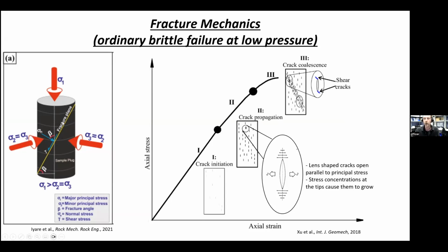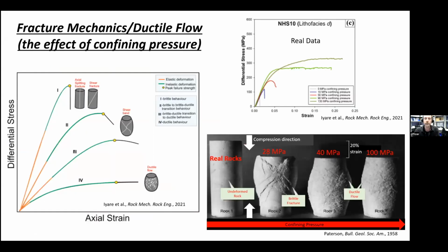So imagine you take this rock and you start to stress it in the sigma 1 direction. Well, what's going to happen is it's going to start getting shorter. It's going to strain, and then eventually, as the axial strain is increasing, you start to generate these microscopic cracks. And then as time goes, these cracks start to get bigger, because you have maximum stresses right at the edge of the cracks, so they start to grow and elongate, and eventually they'll start to interact with one another, and they call this crack coalescence. And then you can start to have a shear band forming, and eventually the rock will break, at least at low pressure. So this is just an example of that.